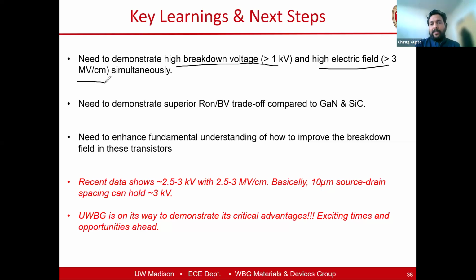So in this regard, our group has been working on this problem for about a year now, and very recently we were able to get close to 2.5, 3 kilovolt breakdown with 2.5 to 3 megavolt per centimeter in a lateral device. To make it simple to understand, roughly 10 micron of source-drain spacing in these ultra wide bandgap transistors can hold close to 3 kilovolt. We are in the process of understanding these results and publishing them, so hopefully you'll see it soon.